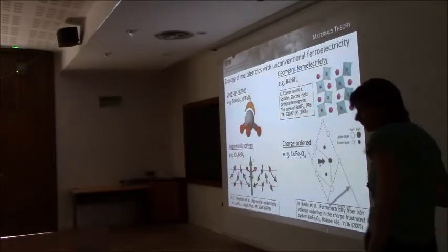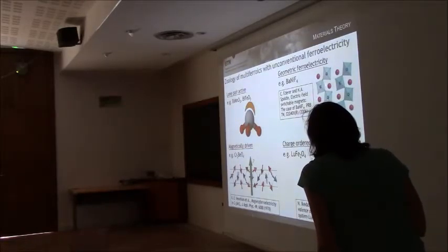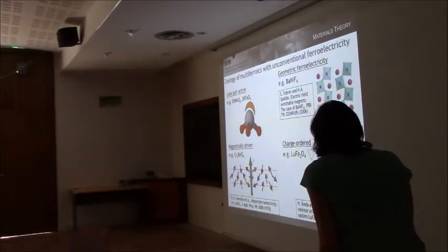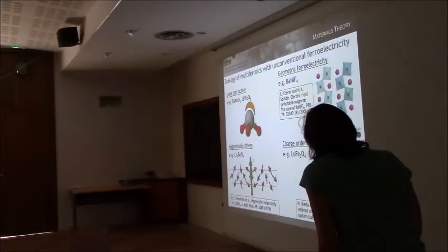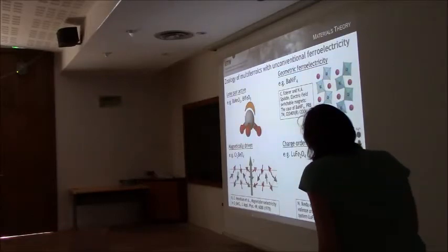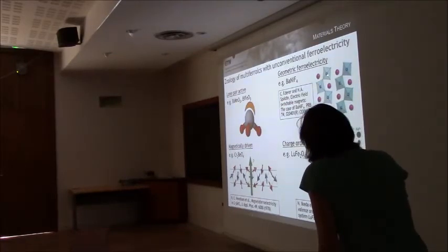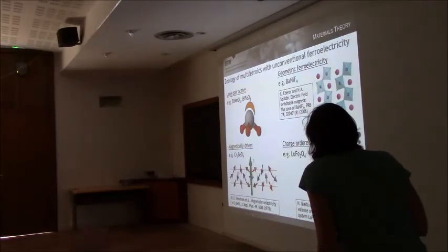And then the last example that I'll discuss next time in a bit more detail is what's called geometric ferroelectricity. And in this case, the centrosymmetric structure has the cubes kind of all perfectly lined up. And this particular material is not an oxide, actually, although this does also happen in oxides, barium nickel fluoride. The structure has this rotational instability, and the rotations are also polar. So as this material rotates, it pushes the cations out of the way and makes an electric polarization. So we'll talk about these four in a little bit more detail next time.